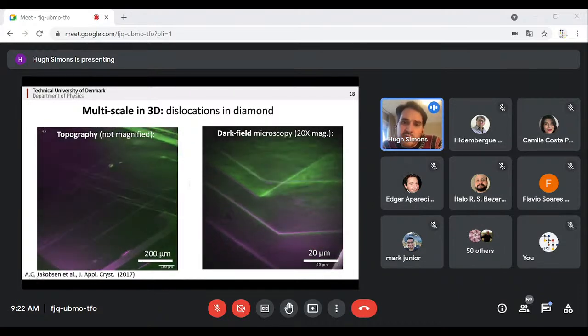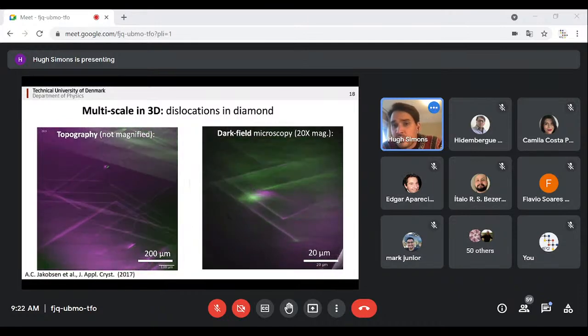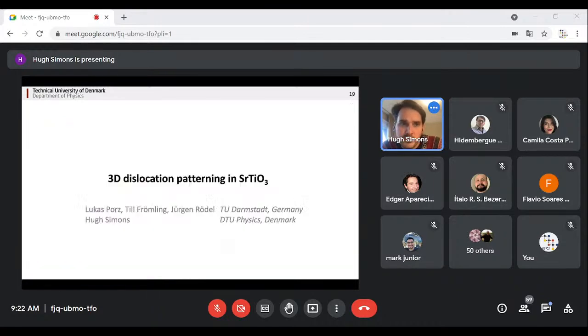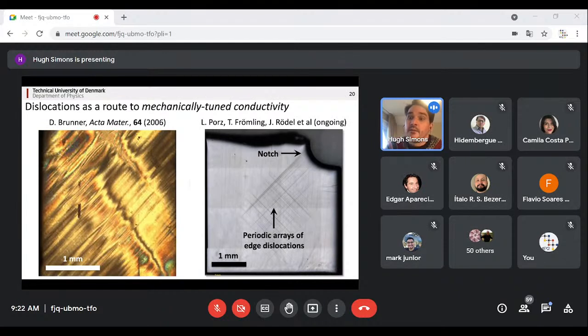So this was just an interesting case. We thought, okay, maybe we can visualize dislocations in 3D and in bulk materials. Can we do something else? So we got talking to a collaborating group at the University of Darmstadt in Germany, and they were working with strontium titanate. So it seemed a bit crazy to do dislocation studies in ceramics because ceramics are not particularly well known to be plastic. But actually, it turns out that if you orient something like strontium titanate to exactly the right orientation, it can in fact become very plastic, to the order of 1 or 2% of deformation, which is almost what you would expect to see in metals, for instance.